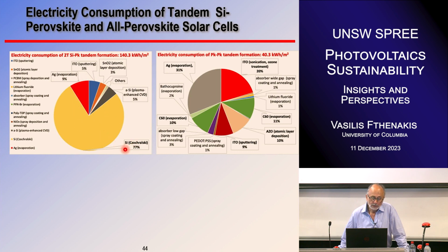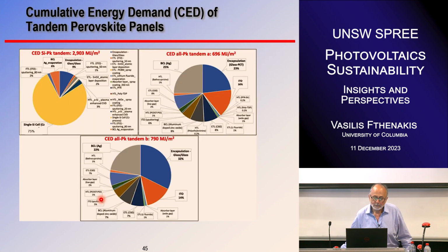Using the single crystalline silicon, about 77% of the electricity consumption is based on silicon. The pie diagram on the right is actually describing tandem perovskite to perovskite. NREL recipes by Joe Berry and others there, and cool. So a lot less energy because they don't have the silicon. And obviously to make the panel, you have to add the encapsulation. So glass to glass has about 9%.